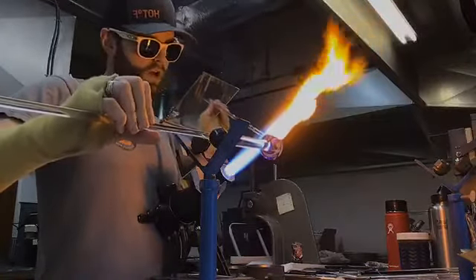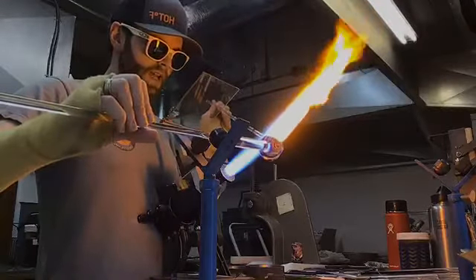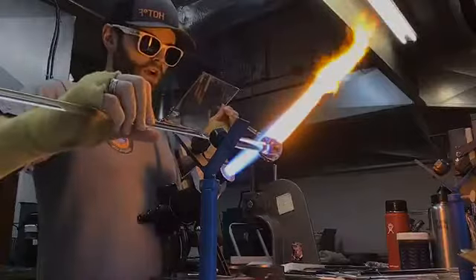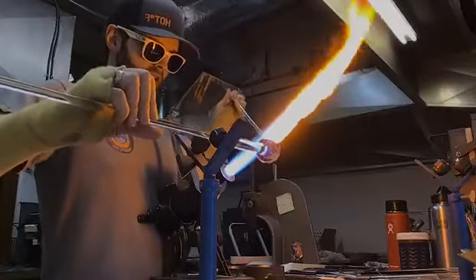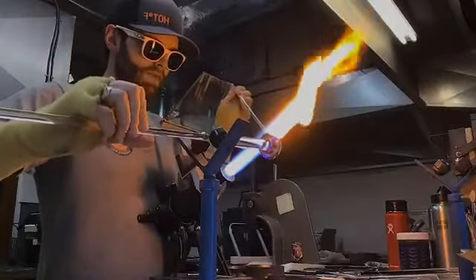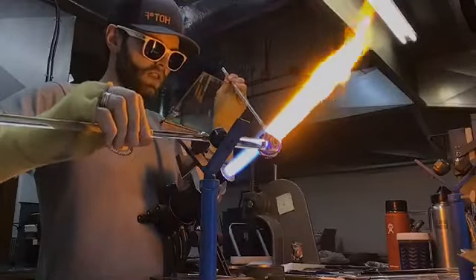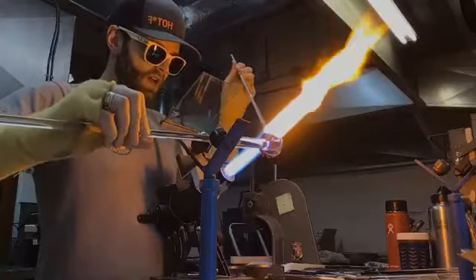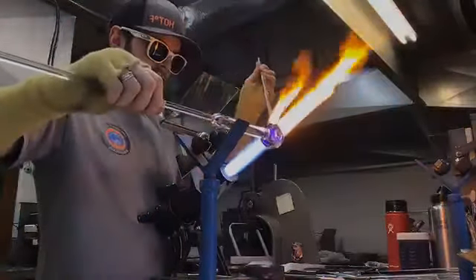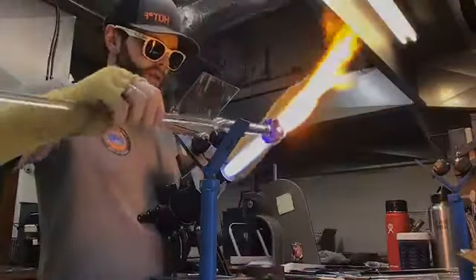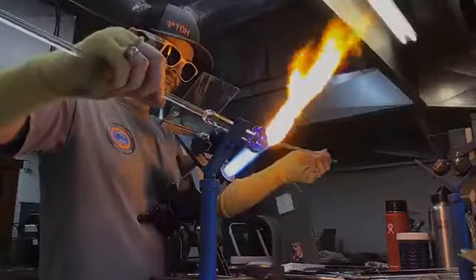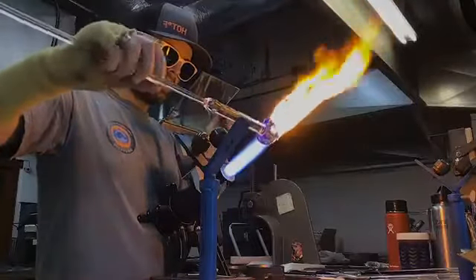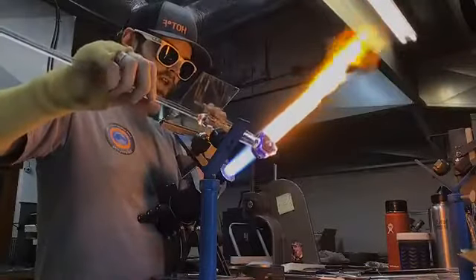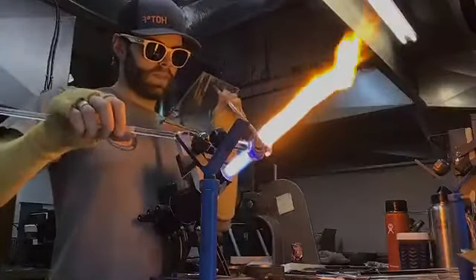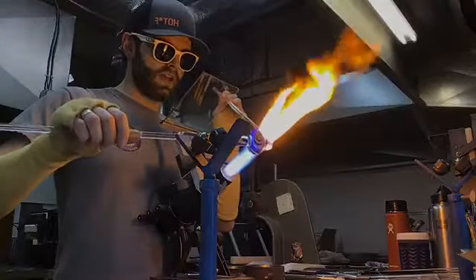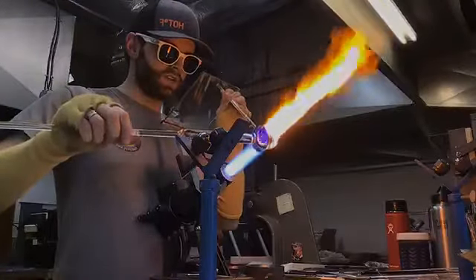And really, I would say this part of the process right here is probably one of the biggest secrets to the vortex as far as understanding how it works. Once I get this clear layer on there, I'll show you guys, but you'll be able to pretty distinctively see the vortex still inside of the clear glass, but the outer shape is still more spherical. So that, in essence, is the trick to making a vortex marble. It's maintaining your cone on the inside and building the outside into a spherical shape.